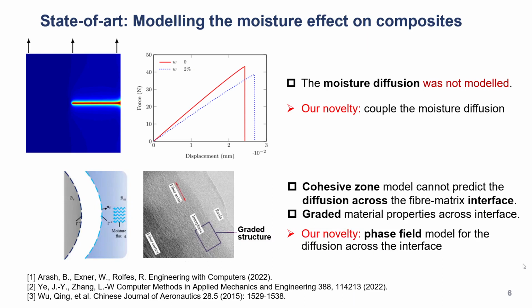In other recent papers, people have argued a cohesive zone model is really difficult to use to predict the diffusion across the fiber-matrix interface because of its sharp interface nature. And also people observe in experiments that the material property across the fiber and matrix interface has a transition. Therefore, our model tends to address these issues by using new phase field models. I will come to that later.